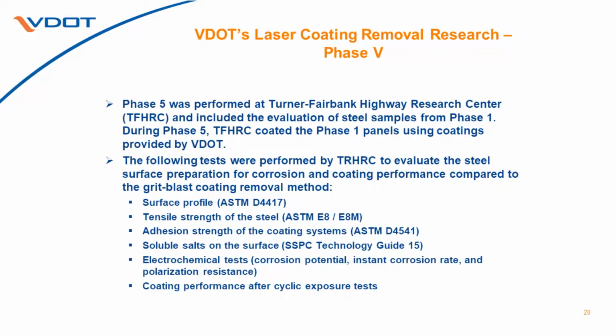We looked at surface profile, tensile strength, adhesion testing, adhesion of the coating, soluble salts, electrochemical testing, and coating performance after cyclic exposure.